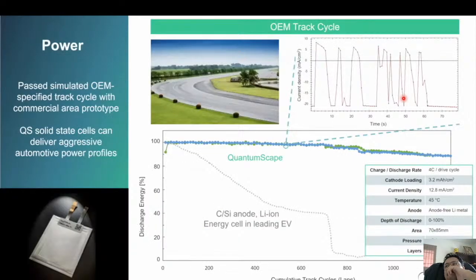So then we put the separators back into a cell and ran what I think is really the most stressful test that I've seen done on our cells. This is a track cycle that we got from our automotive customers. To describe this track cycle for a minute, this shows one lap around the simulated track. Just to be clear, our batteries weren't actually in cars driving around the track. We just took this drive cycle and did it on our single layer pouch cells.